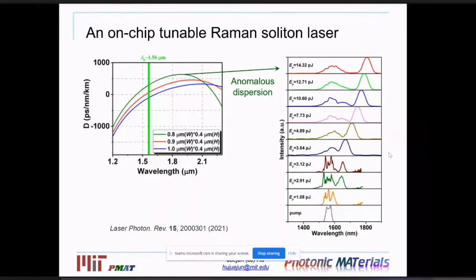Now, this allows us to create a unique tunable light source that can scan across a wide spectral range, but without any mechanical moving components. One more thing I want to mention is that compared to other types of fiber-pumped Raman soliton lasers, our on-chip waveguides feature much stronger light confinement to amplify the nonlinear interaction, and as a result, we can achieve a tunable laser with much lower pump power. The pump power of this laser is on the order of a picojoule. This is 3 orders of magnitude lower compared to its counterpart in a fiber platform. So again, this is beneficial if you're trying to create on-chip sensors with low power consumption.